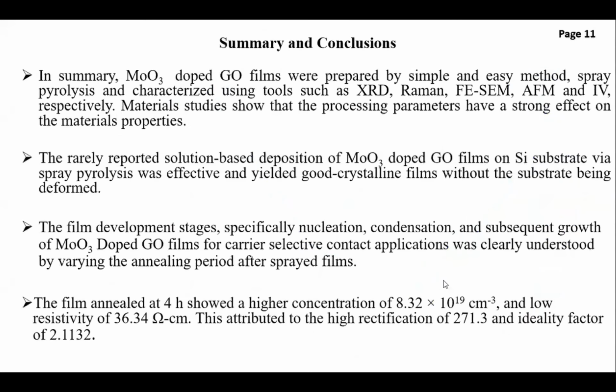In summary, or in conclusion, the molybdenum doped films were prepared by a simple and easy method, which is spray pyrolysis, and characterized using tools such as XRD, Raman, FESEM, AFM, and IV respectively. The material studied showed that the processing parameters have a strong effect on the material's properties. The rarely reported solution-based deposition of molybdenum doped graphene on silicon substrate via spray pyrolysis was effective and yielded good crystalline films without the substrate being deformed.